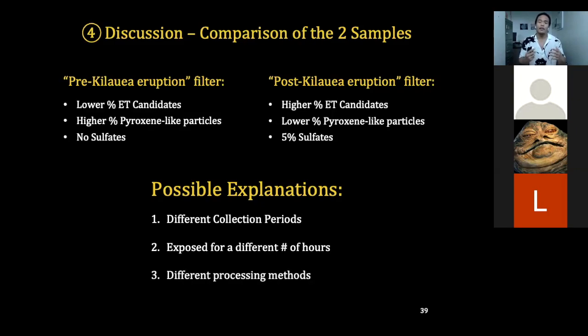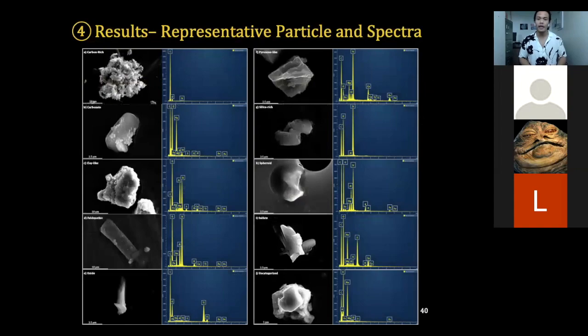Finally, we processed them using two different processing methods. Again, just as a reminder, the pre-Kilauea eruption filter was processed using the concentrating method with a water washing, and the post-Kilauea eruption filter was processed with a stamping method without any water washing. And so what we think is this water washing contributes to a potential breakup of the particles in our filters, as well as the loss of the more soluble particles such as sulfates. And that is a likely explanation as to why we weren't able to see any sulfates in our pre-Kilauea eruption filter.